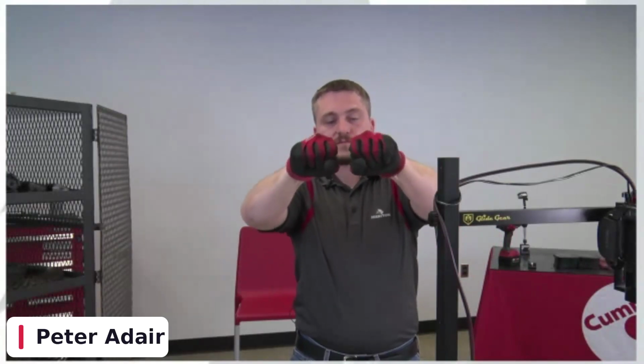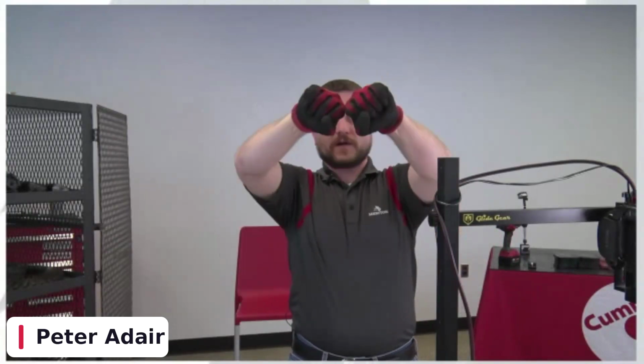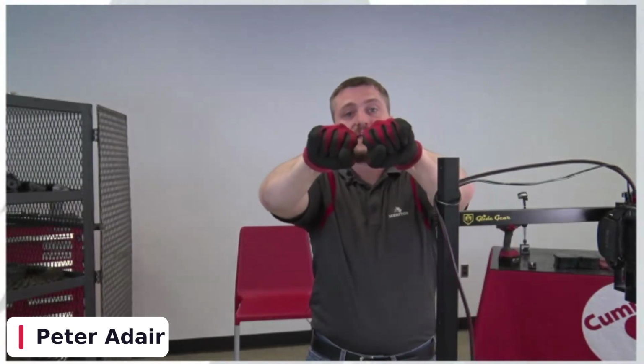So what beach marks are is essentially what I call the coat hanger. All of us have taken a metal coat hanger and bent it in half, right? When it comes to fatigue failures, we're looking at a balance between cycle versus load. Meaning, if I take a coat hanger and bend it like this, how long is it going to take me to bend through it? An eternity. Versus if I go all 90 degrees and back to 90 degrees and 90 degrees again, that coat hanger is probably going to break in 3 bends. Versus like this, it's going to take hundreds of cycles to get the crack to form and the break to happen.